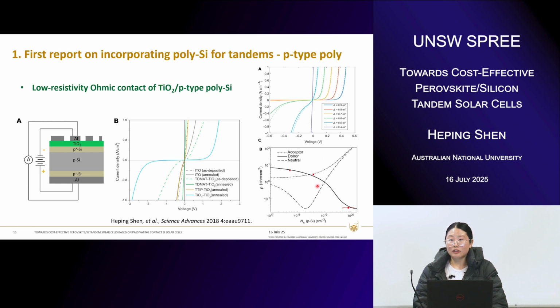And on the other hand, the doping density is also very important. Doping species also plays a role. For example, for the P+ silicon itself, we find that when we enhance the doping density to a level of about 10^20, or even to the regime of 10^21, that allows us to have such a low resistivity contact.